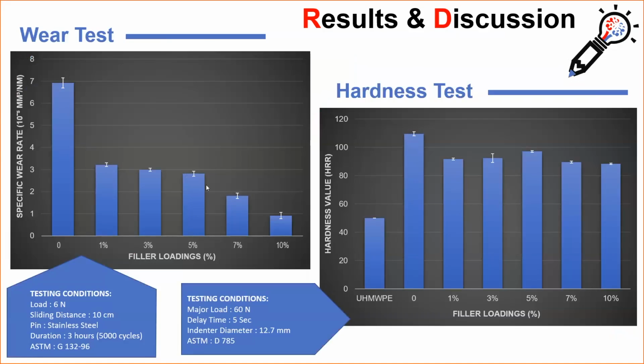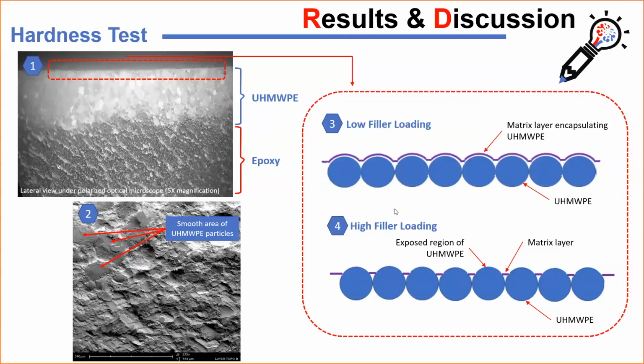On the other hand, the encapsulating layer of epoxy seems to not be the case for the high filler loading composite, where the filler-filler interaction seems to be dominant compared to filler-matrix interactions, whereby clusters of ultra-high molecular weight PE are formed. With all these clusters pushing to form the top layer, at the same time they push away the vicinity epoxy resin, causing a lack of resin layer on the top surface, as illustrated in this figure 4.